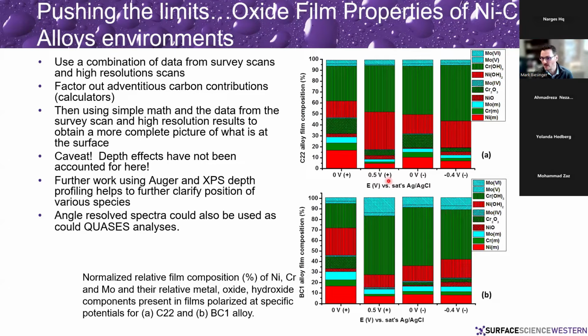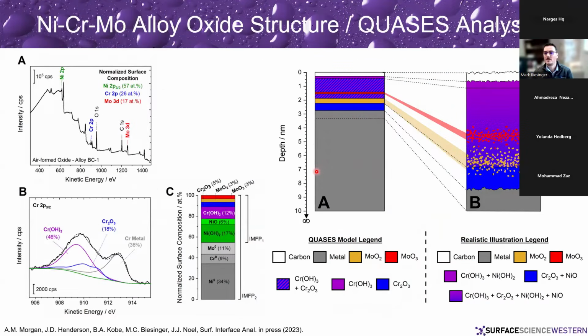In this case, depth hasn't been taken into account, so these are just the overall amounts of the different compositions of that surface that are present. If we start including depth effects, which can get very complicated very fast, you can really pull apart what you have at the surface of a thin layer on these sorts of systems. So this was a nickel chromium molybdenum alloy oxide structure that we did something called QUASES analysis on. And what QUASES analysis does is it looks at the inelastic loss structures above the peak.